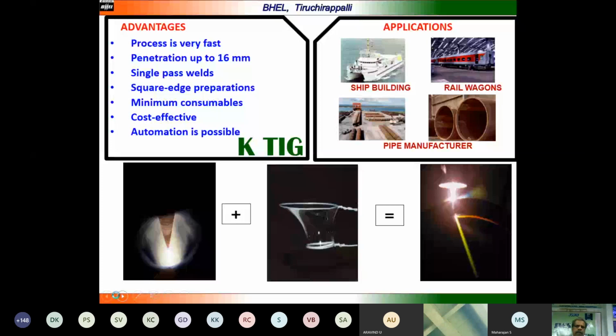It is a very fast process. Up to 16 mm, the claim is that it can penetrate easily, in a single pass with square butt edge preparation, much better than the activated TIG welding where I told 12 mm stainless steel. Here it is 16 mm stainless steel. Minimum consumables are used, it is cost effective, and automation is also possible using this process. It can be used for shipbuilding, railway wagons, pipe manufacturing, all these. This is the advantage of this process.